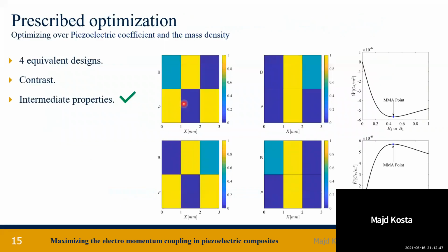So with that being said, and in order to study the influence of the parameters of the objective, we optimize W with prescribed fixed properties. For example, in here, we optimize the electromomentum coupling over piezoelectric coefficient and mass density. The other properties are fixed and equal for each layer.